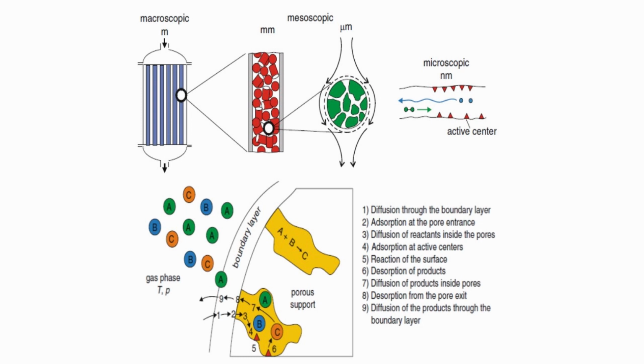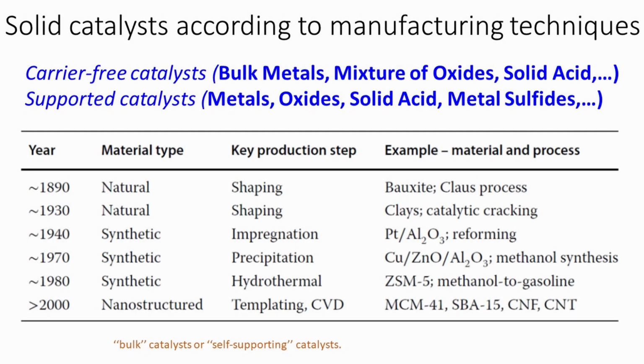The microscopic scale involves the structure of the active sites. The mesoscopic scale covers the pore system and the size of support particles, as well as the particles of the active phase. The importance of the microscopic scale goes without saying, as it determines the intrinsic activity and selectivity of the catalyst. The mesoscopic length scale affects, among other things, the interparticle mass transfer of the catalyst. The macroscopic size and shape is relevant for properties such as pressure drop in a fixed bed reactor, mechanical strength, and attrition resistance.